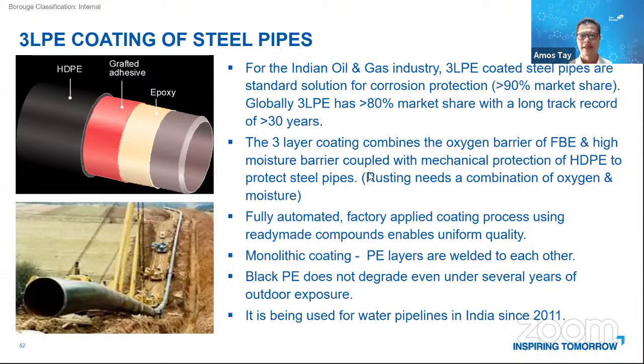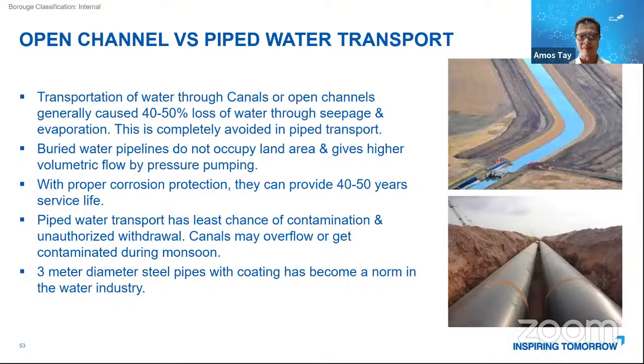This is a standard configuration. For the India oil and gas industry, 3LPE coated pipes are the standard solution for corrosion protection of the steel pipe, because of the exposure to the elements. It's about 90% of the market share. And globally, 3LPE is about 80% market share with a long-term record of about 30 years. This 3LPE combines the oxygen barrier of FBE, which is fusion-bonded epoxy, and high moisture barrier with mechanical protection from HDPE, which protect this steel pipe. We all know that rust comes about when you have oxygen and moisture. If you block oxygen and moisture from the steel pipe, you are protecting the steel pipe from corrosion. And this application can be fully automated so that the material is of good quality.